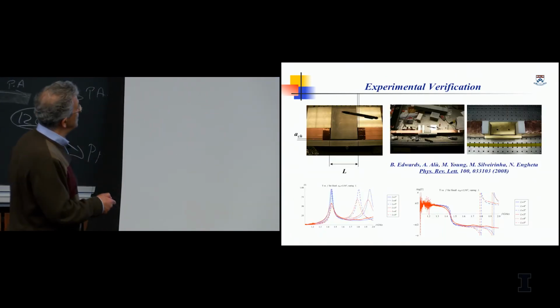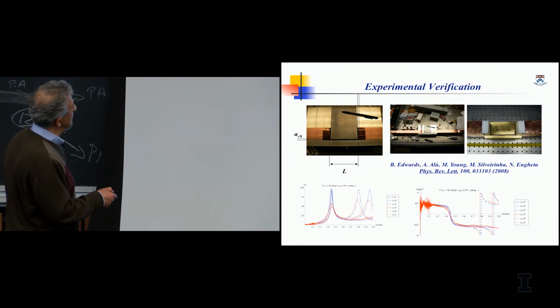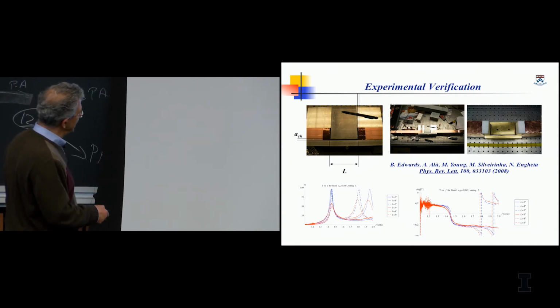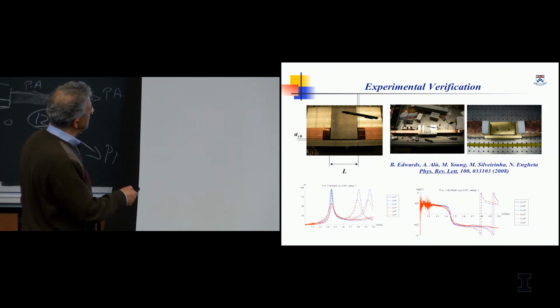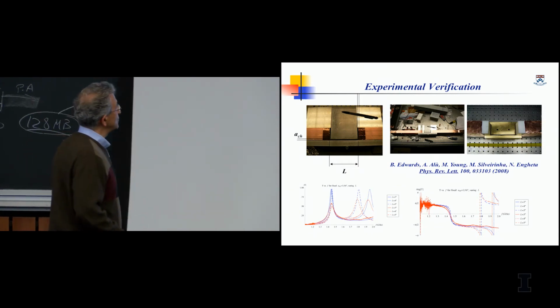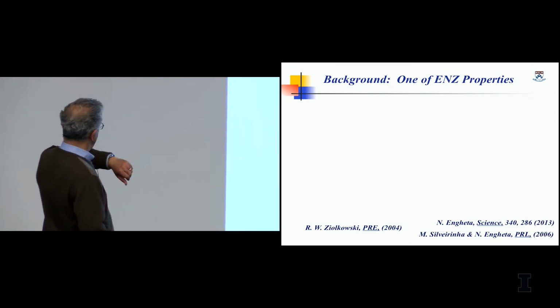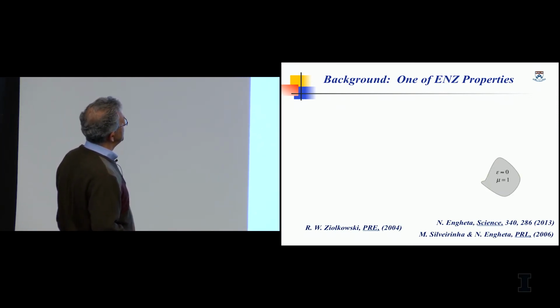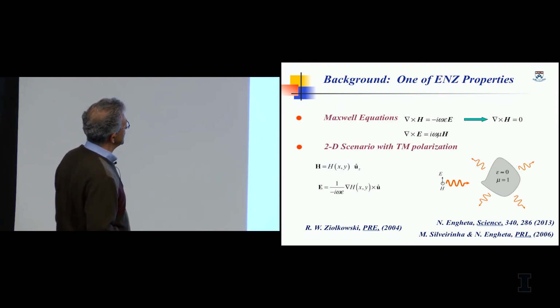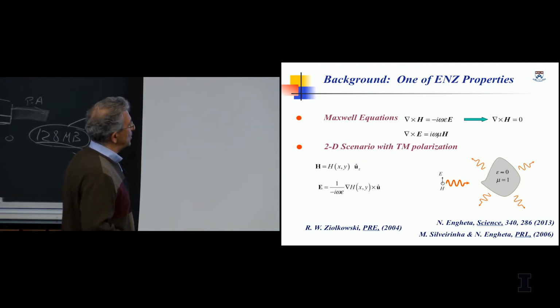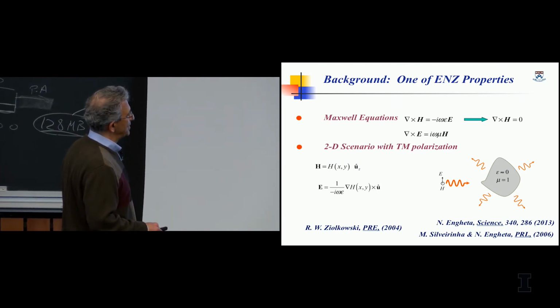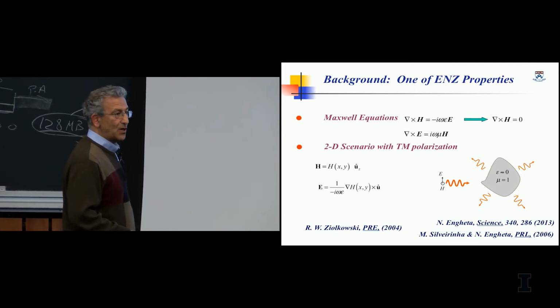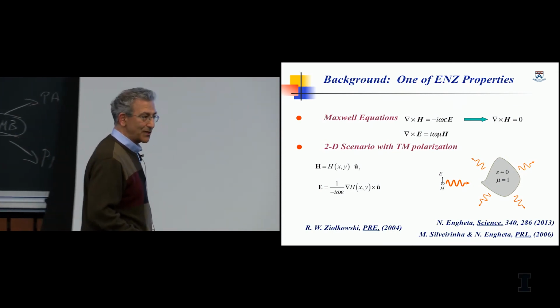What we did in the experiment, by the way, was use the waveguide at cutoff, and indeed we showed that even though you change the width over here, you still have the transition going through. Now, in the interest of time, let me just jump over some of these properties of photonic doping, and then we can stop. One of the interesting points is that if I start with a structure like this, the magnetic field around here is completely uniform in this structure.